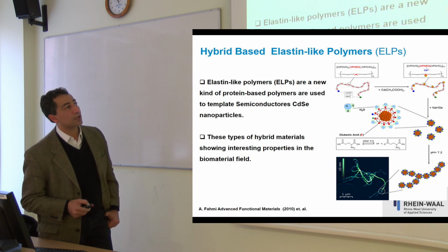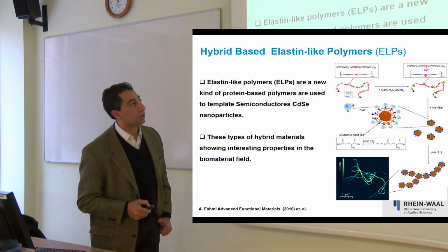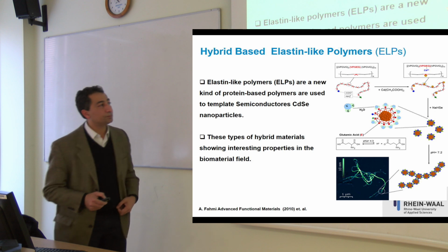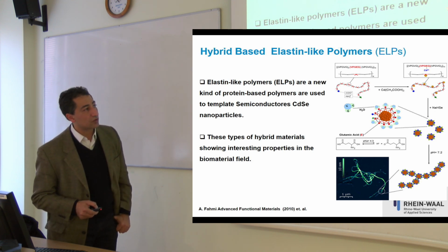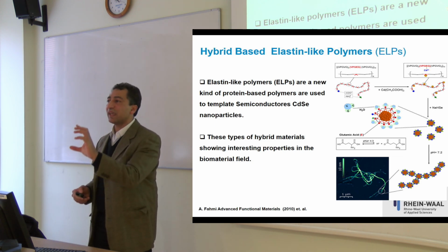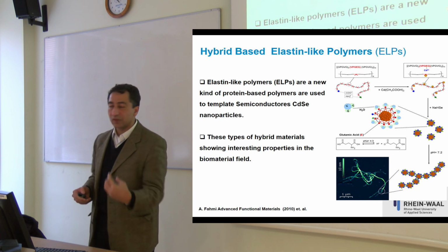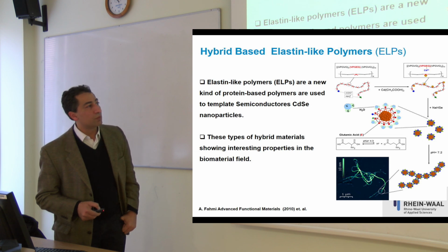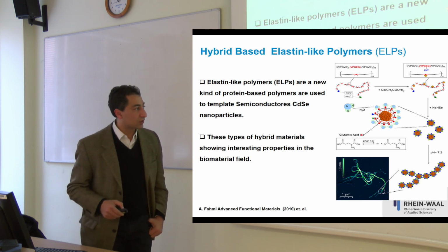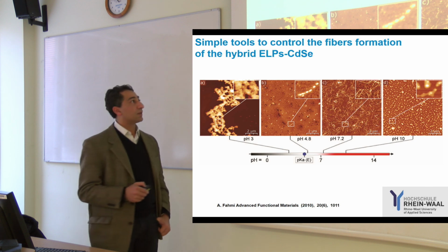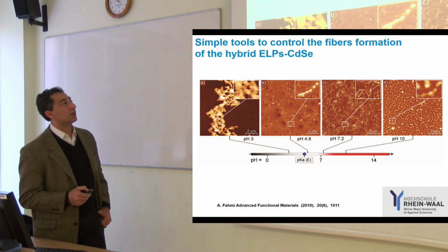We try to use the in situ approach so that we can have what we call a core-shell structure. We have the inorganic inside, coated with the organic outside. In this case, we use a precursor, cadmium. I will tell you later on why it's cadmium. In this case, we make this different core-shell structure. As I mentioned before, we change only one amino acid so that we can charge it. We like to induce what we call a driving force. In this case, we use electrostatic interactions. We put this together so that we can have a nanofiber based on a hybrid material, organic and inorganic. The organic is the elastin-like polymer. The inorganic is this kind of metallic structure, so that we have this fibril-like structure. As I mentioned before, in this case we use cadmium. The cadmium is very unique, as we have done in Denmark, in that we can use it as a precursor to make inorganic semiconductors.